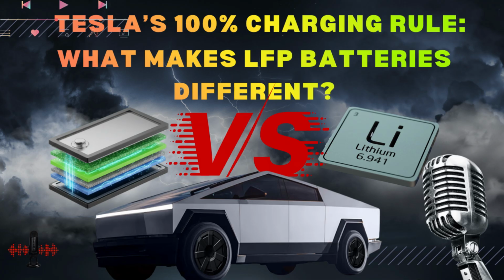So let's wrap up this deep dive with the core takeaways. We started with this universal anxiety of fast-dying batteries, and we discovered that the cure really lies in a fundamental shift in the chemistry. We established that standard NCM batteries are these high-energy but fragile sponges that just tear and clog themselves up over 1,000 to 1,500 cycles. But LFP batteries, because of that incredibly strong phosphate bond, are rigid, non-moving steel cages that maintain their integrity through 3,000 to 6,000 cycles. That structural stability just dramatically slows the whole aging process.